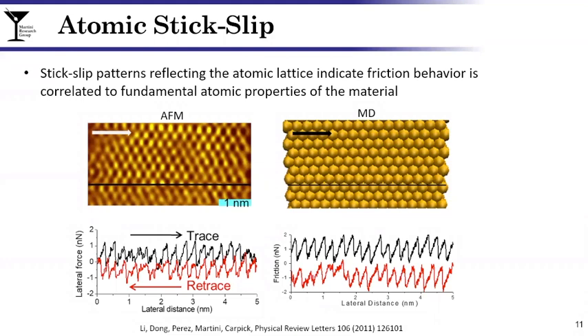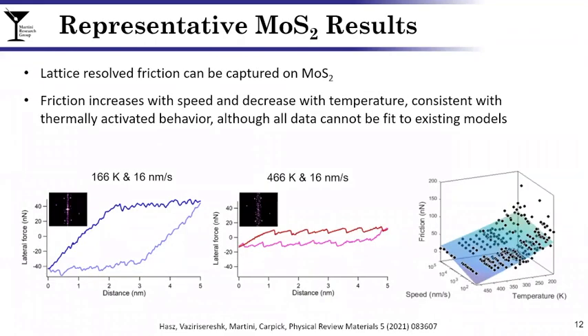Shown here are some representative AFM results, again from Rob Carpick's group. What you're looking at is friction measured at different speeds and different temperatures. And in each case, you see the sawtooth pattern indicating that the friction is correlated to the atomic features of the surface. And we see here that although we were trying to simplify things, in fact, the single asperity friction does reflect some of the behaviors observed on larger scales, namely the temperature and speed dependence.